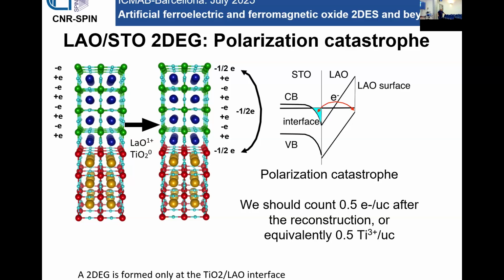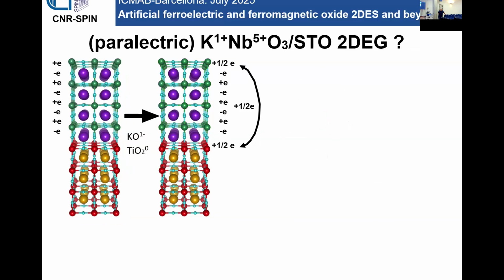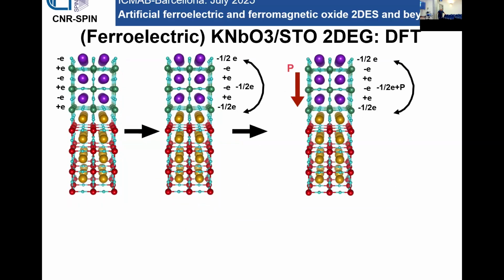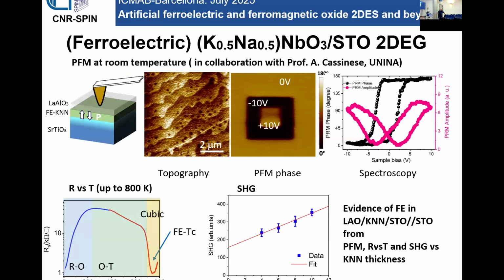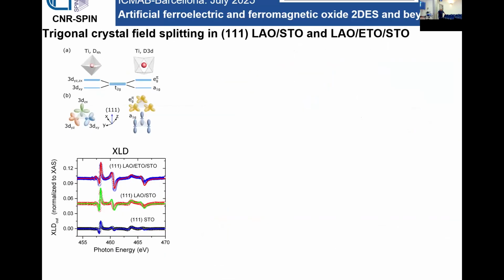Lanthanum aluminate is an amorphous layer. We grow it because the potassium niobate is not stable in air, so you get water. That's important. Regarding barium titanate, yes, we have done that, but it seems less robust.